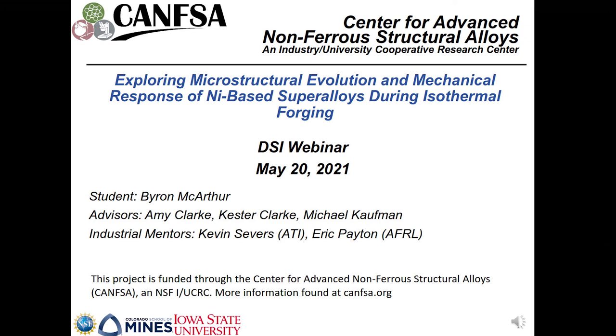And before deformation, for Srinivas Kumar's question, the hold time for the sample. We had evaluated different hold times utilizing the Gleeble to make sure that we were at an equilibrium state for the primary gamma prime fraction. And we held for several minutes.